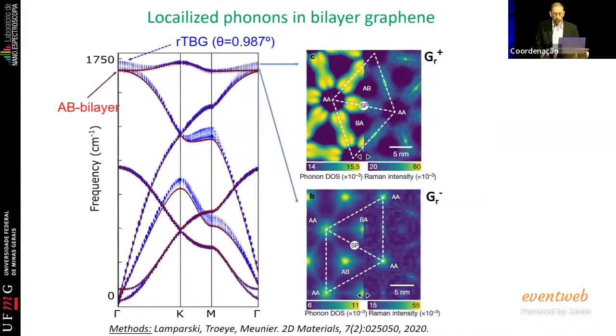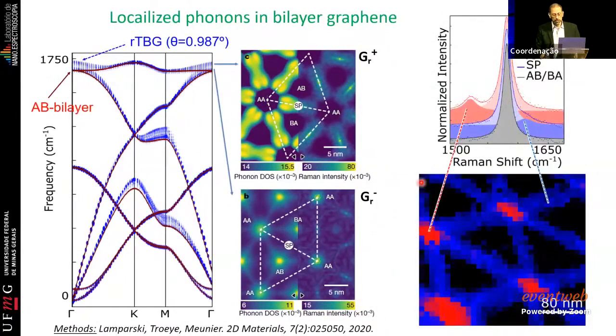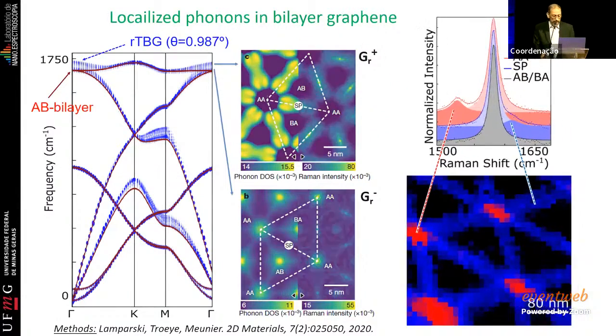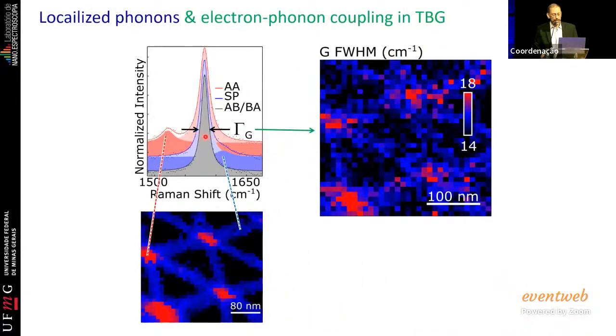And when we now go with the nano optics and measure it locally, you see that when you come to the AA sites, besides the usual peak here that is related to the carbon-carbon stretching, you see an extra peak appearing here that is very much like predicted for those small frequencies. And when you look in the soliton strain region, the domain walls, you'll see a new peak appearing here, very much like predicted theoretically. And you can also look into the width of this peak, and plotting the width of this peak in space, you see that the width also shows the structure.